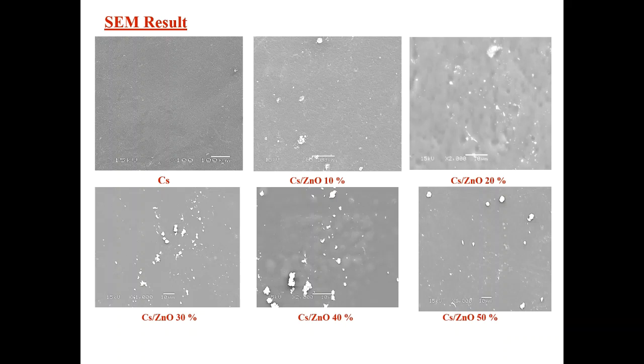Also, scanning images for chitosan and chitosan zinc oxide samples show that the chitosan surface has small pores that are distributed non-uniformly on the composite surface. The pore size increased with the addition of zinc oxide, and with increased weight percentage of zinc oxide, the pores became fewer, with the appearance of white spots regarded as zinc oxide which accumulates on the chitosan surface.